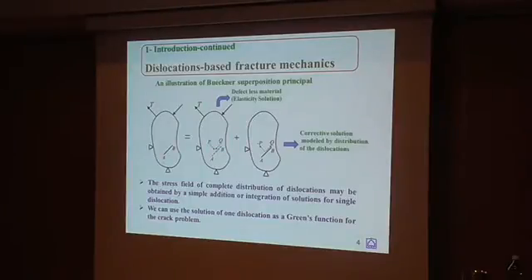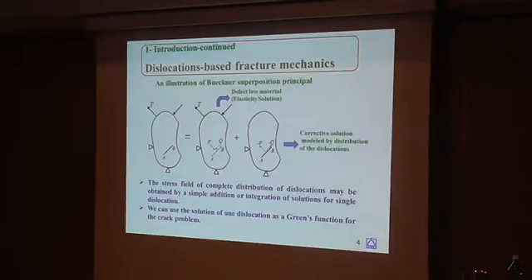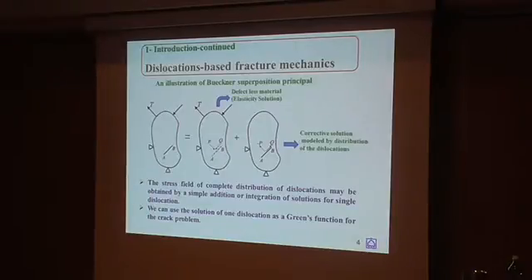In the second and main problem, the corrective solution is modeled by distributing dislocations along the crack. With the sum of these two sub-problems, we reach the main problem: the material with cracks. A complete distribution of dislocation may be obtained by simple addition or integration of the solution for a single dislocation. The distributed dislocation solution serves as a Green's function, allowing use for multiple cracks without any limitation on the number of cracks, and it can also be used for curved cracks.